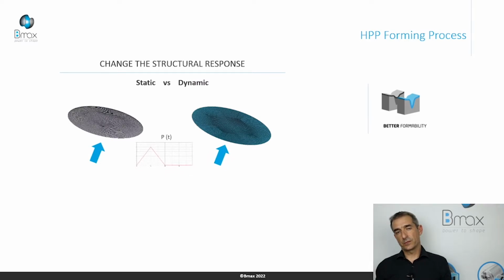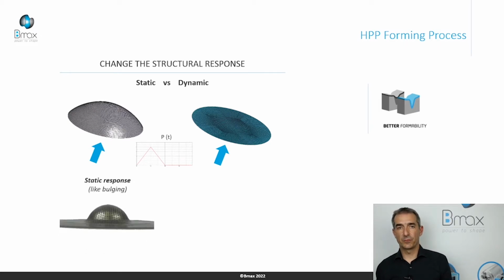If we consider two membranes, the same thickness, the same material, and the same pressure applied on this membrane. If the diameter is small, the stiffness of the structure is high, and the structure can catch all the pressure variation, and the maximum of pressure defines the deflection of this membrane. We have, at the end, the final shape, it's hemispherical. It's like hydrostatic forming, like hydroforming. But it doesn't require a huge hydraulic press, and it's done in a few microseconds. But it's exactly the same structural response as static.